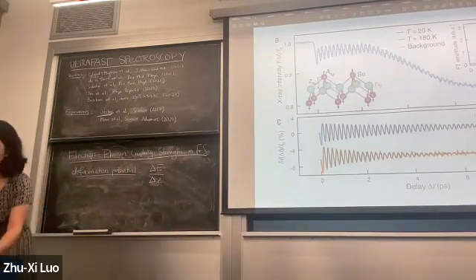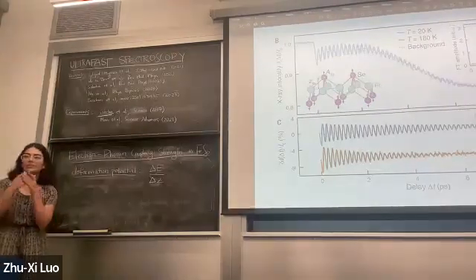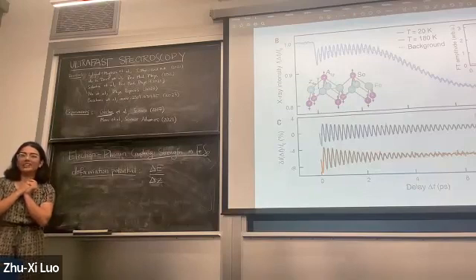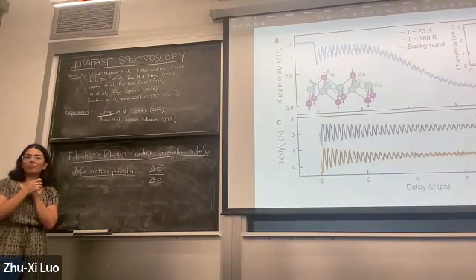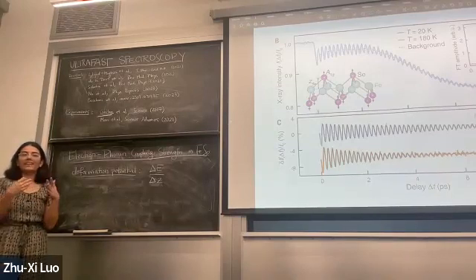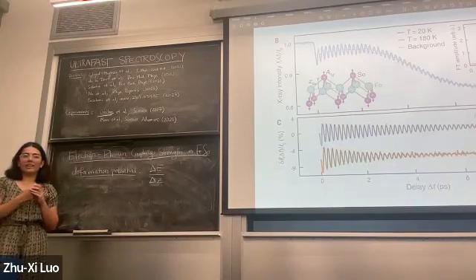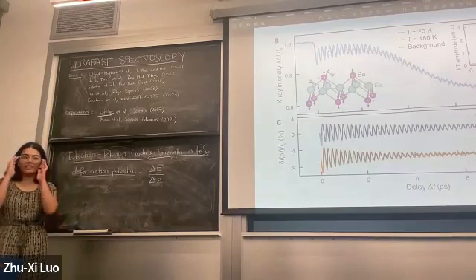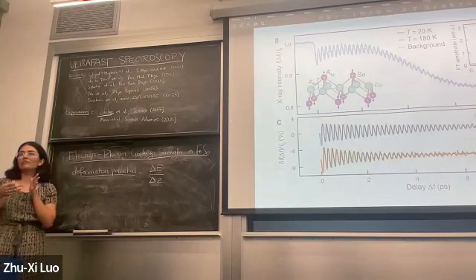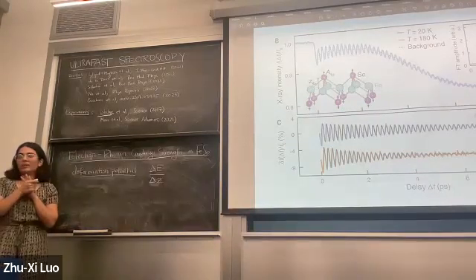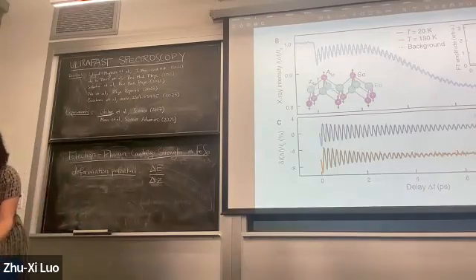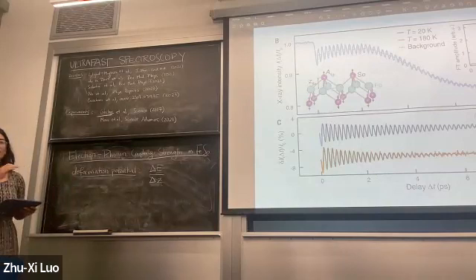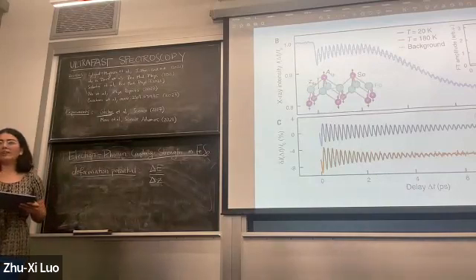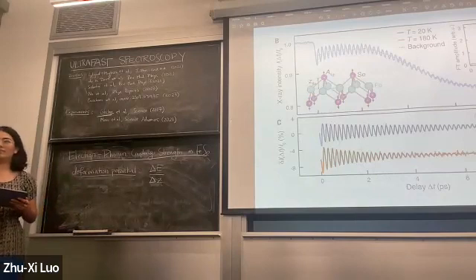Previous experiments attempted to measure this, but they had to do it in a very indirect way using regular, not time-resolved, ARPES data. You can extract information about interactions in your material from ARPES, but oftentimes it requires some non-trivial assumptions about the structure of interactions in your material to be able to extract anything. The goal of this experiment is to use time-resolved techniques to get rid of all of those assumptions and directly measure the coupling between the electronic and the phononic degrees of freedom.